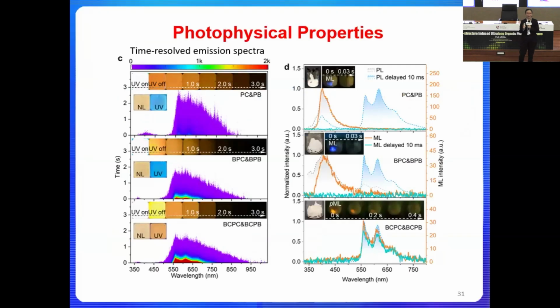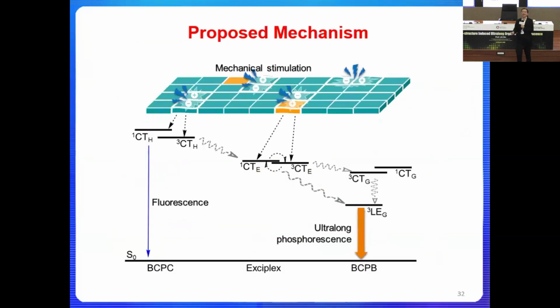All right. So we actually monitor the emission of the mechanoluminescence system after we add in 1% of the dopants. Now we are able to get much elongated emission, no longer at the nano-picosecond level. We can easily see them at the seconds level, right? Just by adding this small molecule.